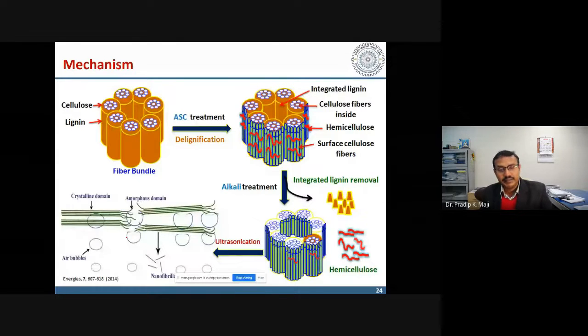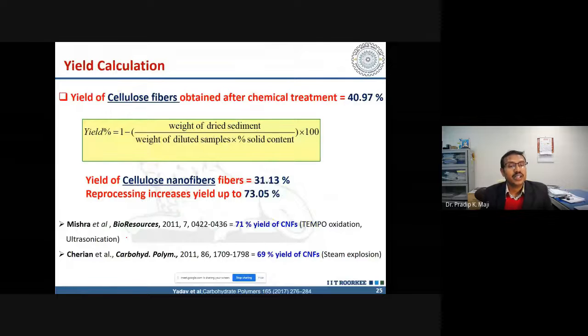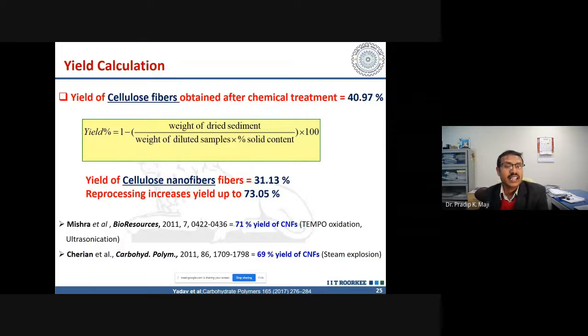This is the mechanism I told you, and we have calculated the yield of cellulose nanofiber. The yield obtained after chemical treatment is 40.97%. Yield is calculated as 1 minus weight by the other; this is the basic equation.